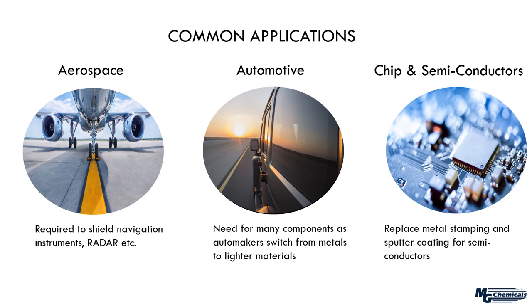If you look at the automotive or transportation industry, these have become highly computerized within the last 25 to 30 years. So there's obviously a big demand for shielding materials. The other thing to note here is that they've tended to switch away from heavier metals, stainless steel, aluminum, that sort of thing that would naturally provide shielding. And they're using lighter materials for higher efficiency. So they're using carbon fiber, and these types of materials need to be metallized. And with the efficiency and speed that you can apply conductive paints, that makes them a very popular choice.